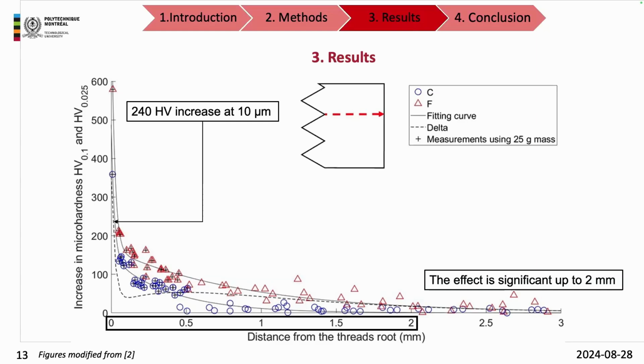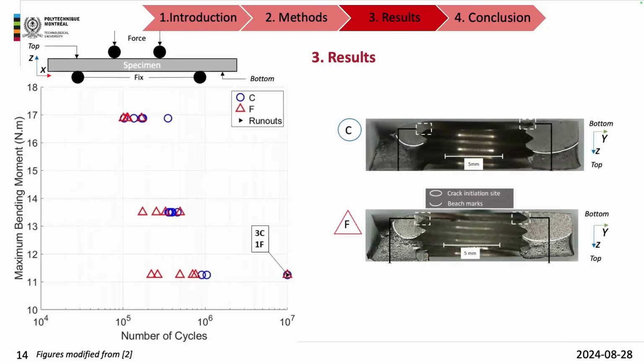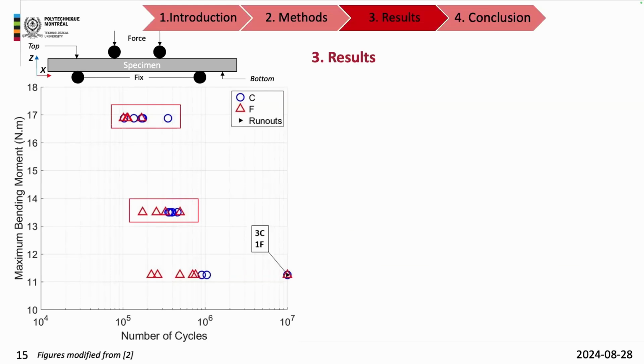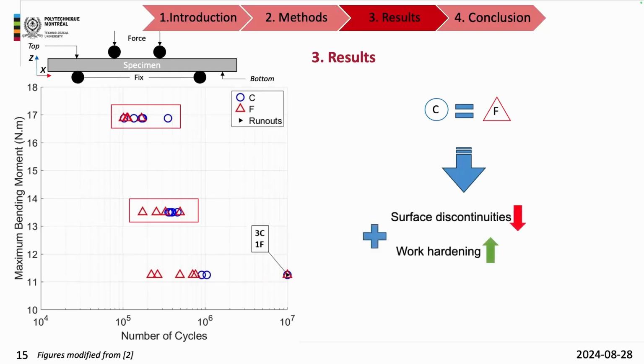Now, let's check if this positive effect on the hardness has an impact on the fatigue life of orthopedic implants. The first thing that we need to show is that all cracks initiated from the first threads counting from the bottom surface, which is in accordance with the 4-point bending test, since this surface is in tension. If we go now into the details, for the first 2 loading steps, we didn't note a significant difference between the average fatigue life of the orthopedic implants, because as I showed you before, there is a specific plastic deformation that induces discontinuities on the flow form specimen, and those discontinuities will compete with the positive effect of the hardening, thus inducing similar lifespan for the flow formed and conventional specimens.